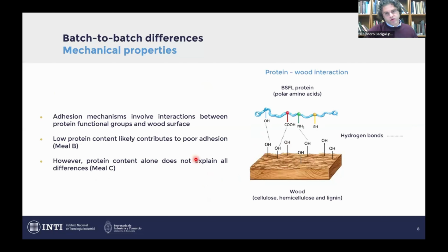So first, we thought the result for meal B is expected because of the low protein content, because the theory of adhesion for protein-based materials is based on functional groups in the protein that could interact with the functional groups on the wood surface. Of course, this was not all, because sample C has similar protein content to sample A, but mechanical properties were quite different. So protein content does not explain all the difference between the adhesives.